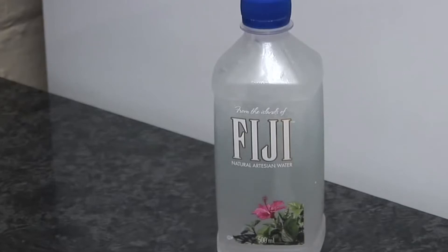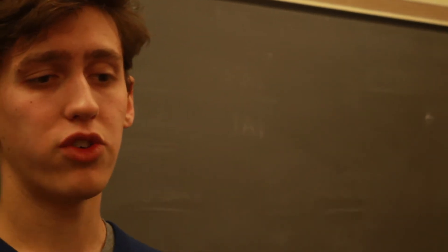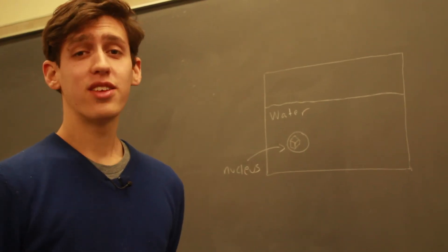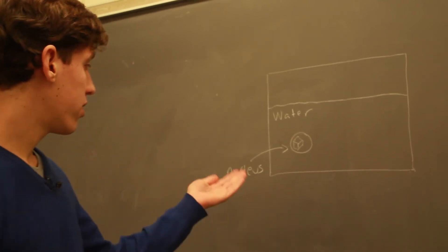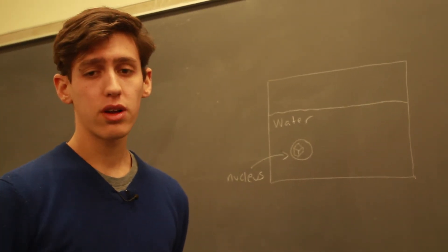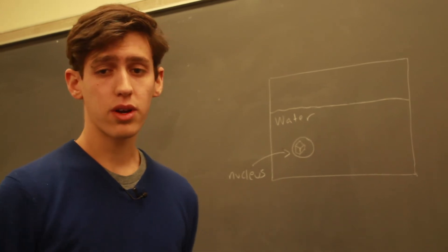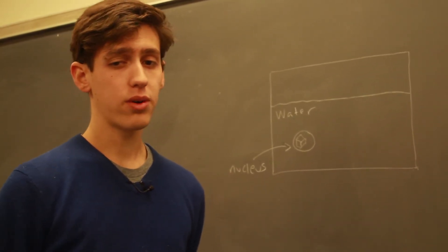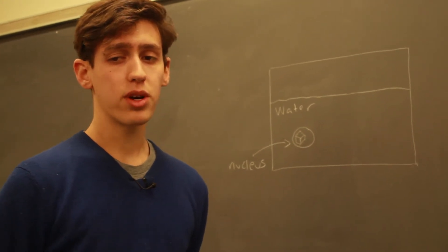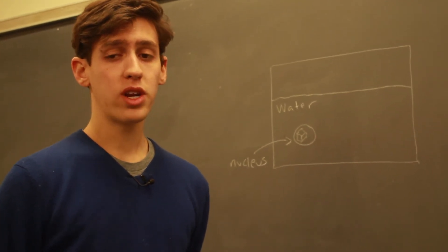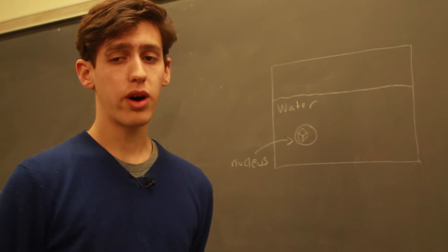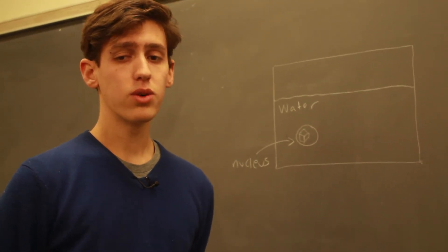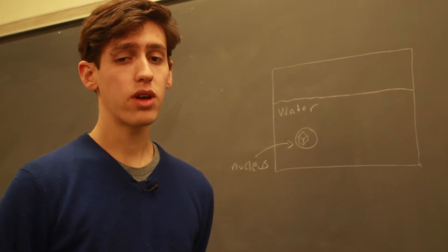So why does this dramatic crystallization occur? The reason is that the phase transition from liquid to solid isn't just instantaneous when the temperature drops below zero Celsius. To turn into a solid, first a small crystal called the nucleus — which you can imagine as a little sphere — randomly forms inside the liquid. This happens all the time, whether the temperature is below or above zero, throughout the liquid. What depends on temperature is what happens to these nuclei. When the temperature is above zero, the liquid state of water is energetically favorable over the solid state, so the nuclei spontaneously shrink and the liquid does not crystallize.